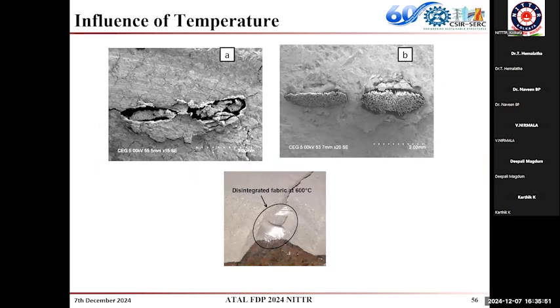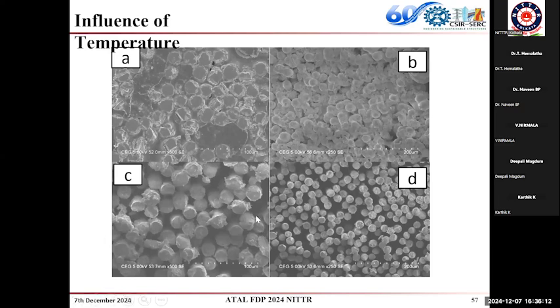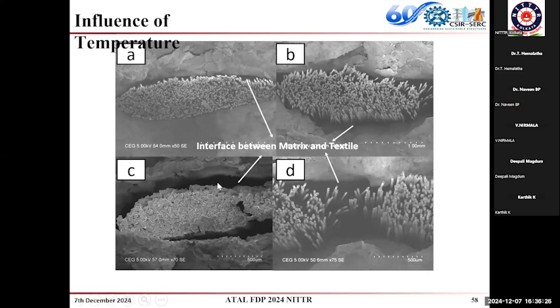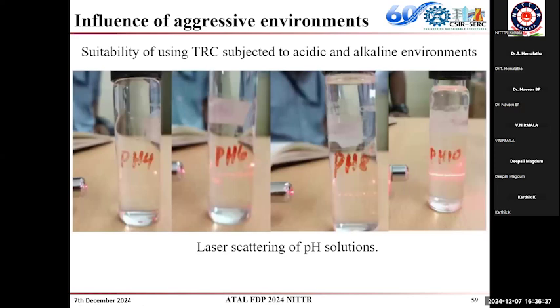And here we have carried out studies to see how it disintegrates when subjected to high temperature, because it has a layer of fibers. This shows that after around 600 degrees, when it is subjected to 600 degrees only, the fibers are getting disintegrated. And these are other studies showing how this disintegration happens under scanning electron microscopy, how the fiber bundles are affected when subjected to high temperature, and how the interfacial transition zone is affected when subjected to high temperature.